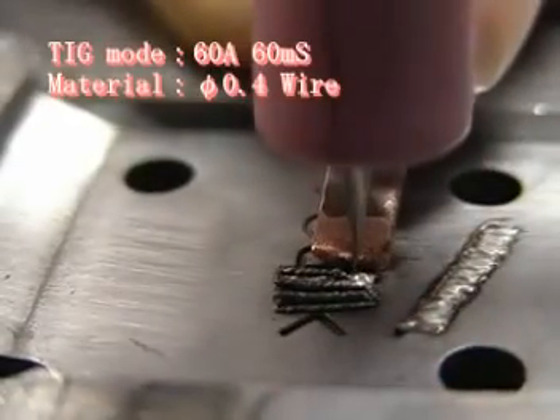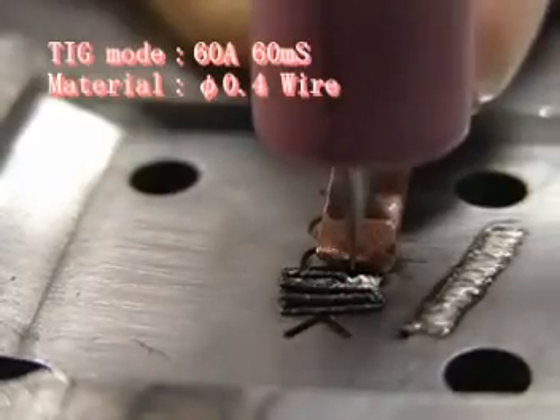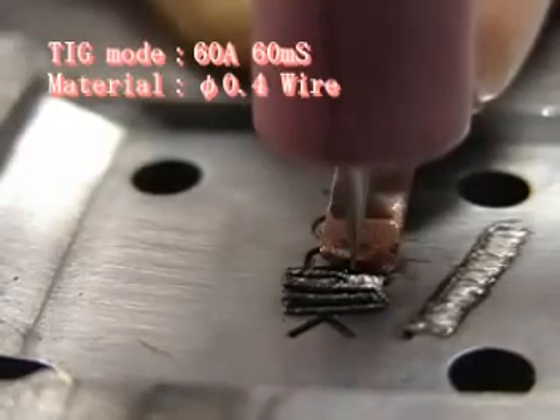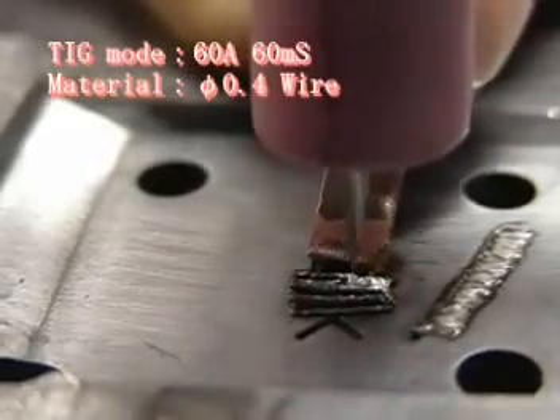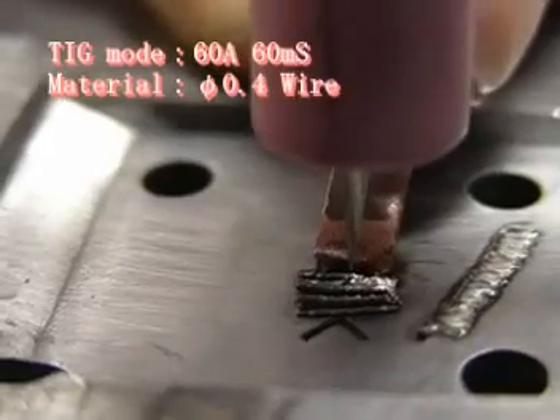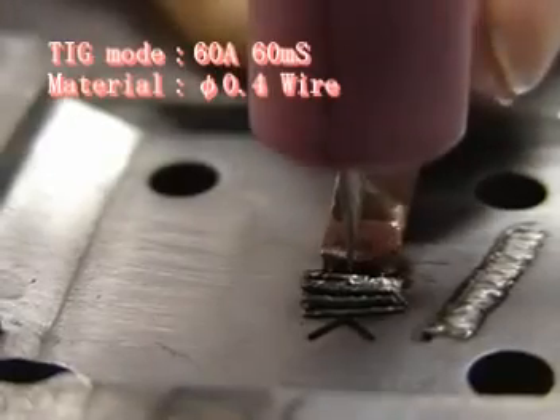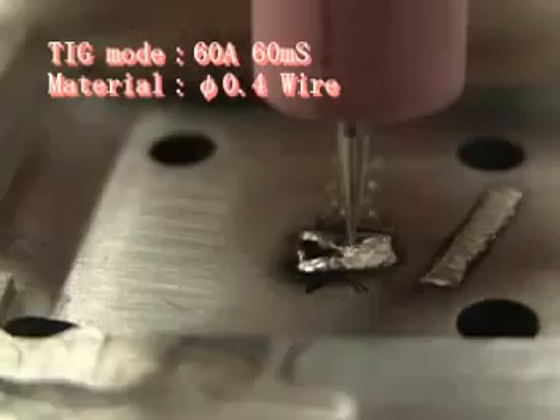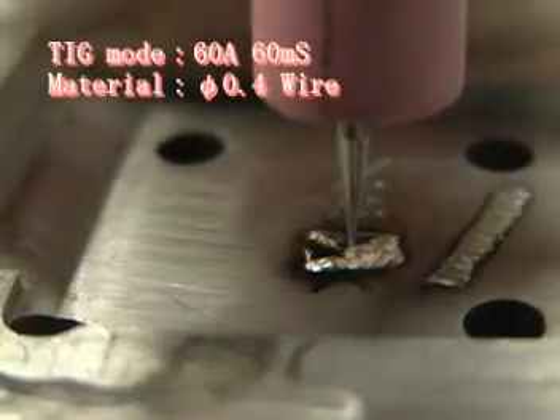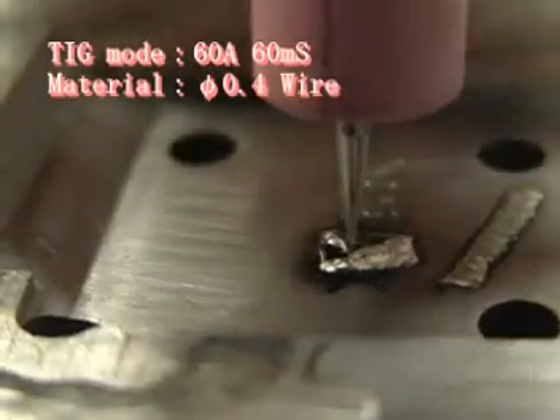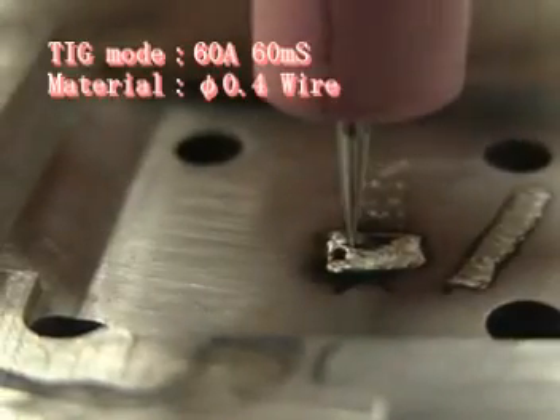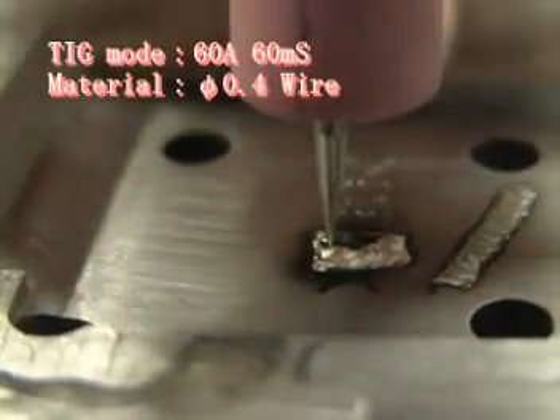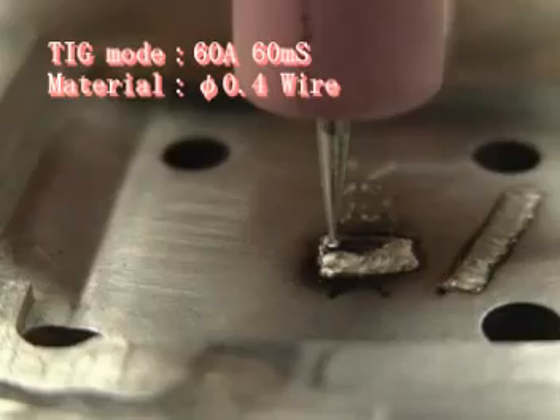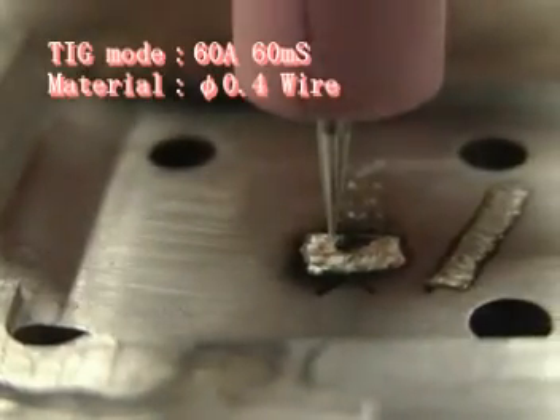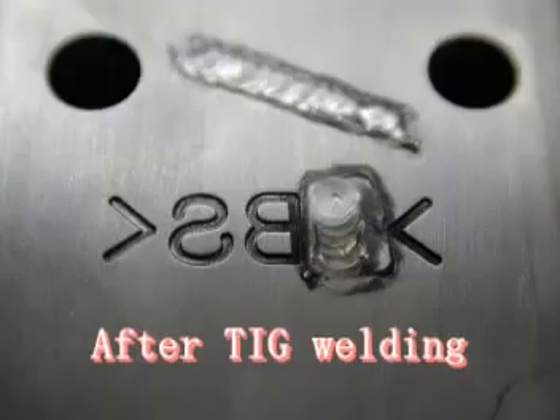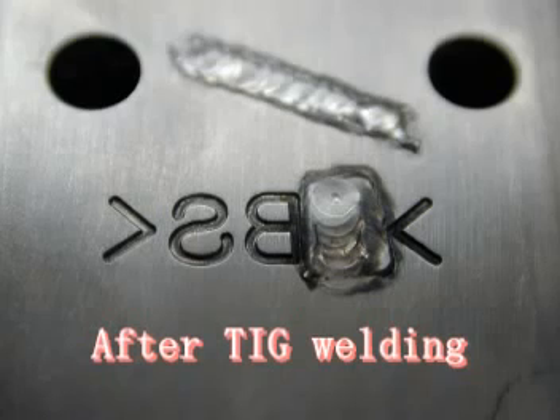Securely weld 2 wires at a time and move a torch slowly to overlap the weld bead slightly. Be sure to protect areas other than the target area by using a copper plate so as not to melt other stamped characters. After melting down both ends, melt the middle part. For secure welding, increase the current and time settings at this point. This is the result of this welding operation.